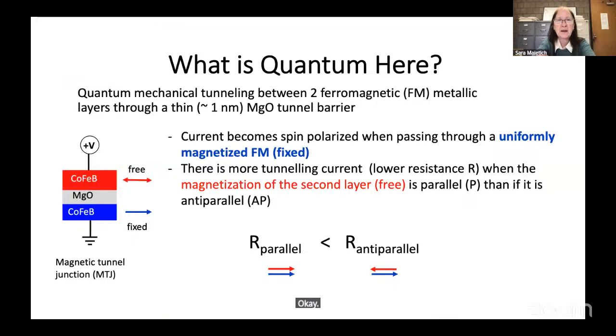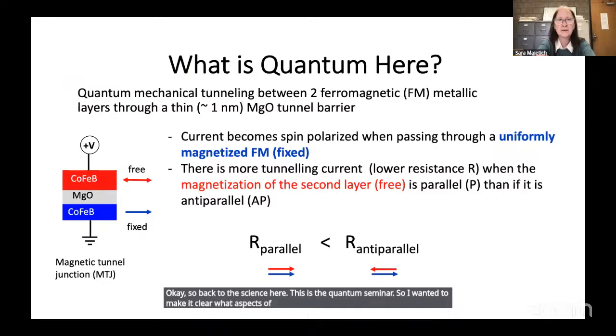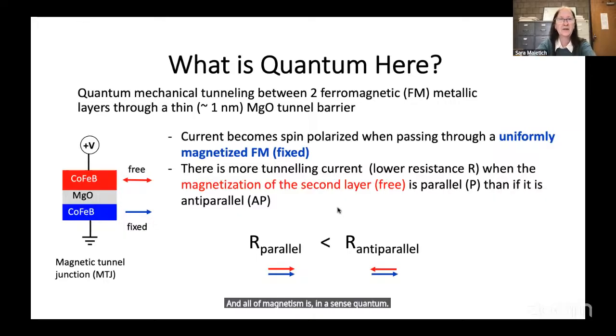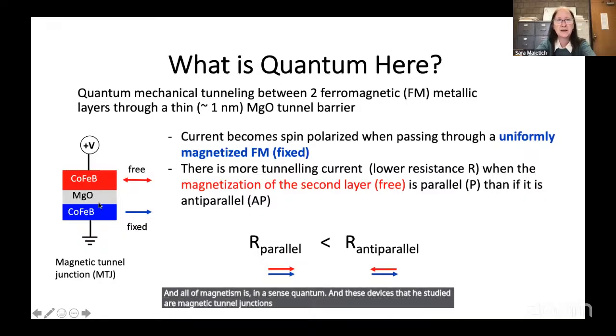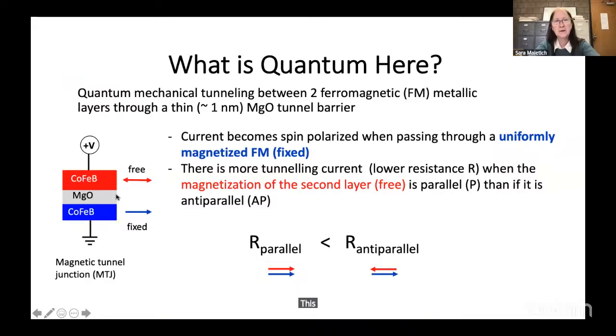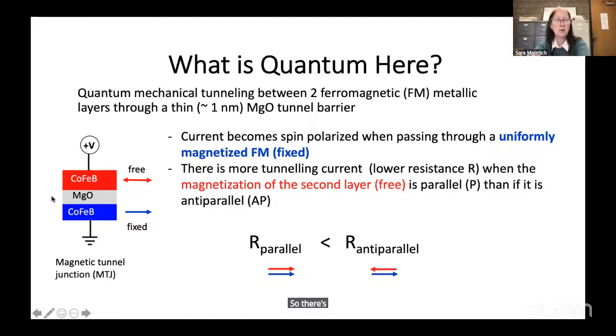Okay, so back to the science here. This is the quantum seminar, so I wanted to make it clear what aspects of what I'll discuss are quantum and what are not. And all of magnetism is, in a sense, quantum. These devices that we studied are magnetic tunnel junctions, so they have quantum mechanical tunneling. This tunnel barrier is very thin, a 1 nanometer magnesium oxide layer. It turns out there's a very special connection between this cobalt iron based alloy and magnesium oxide. If it's crystallized in a certain direction, the tunnel barrier has a spin filtering effect, even though it's not magnetic at all. So there's a reason that people working in the magnetics area like this combination for their basic device.